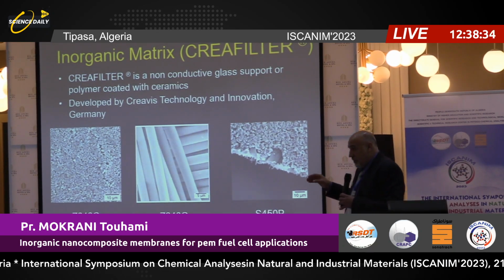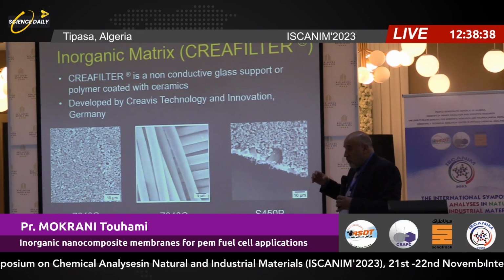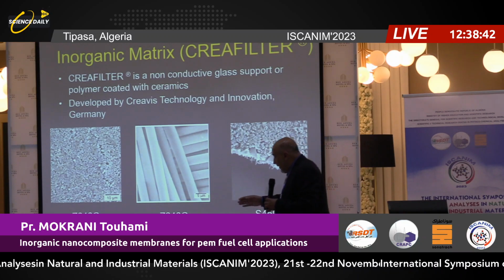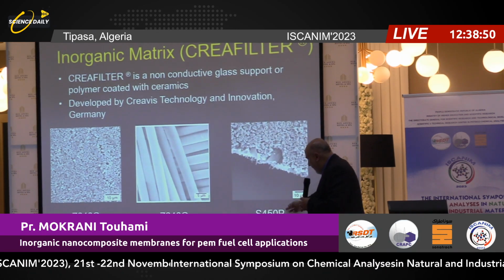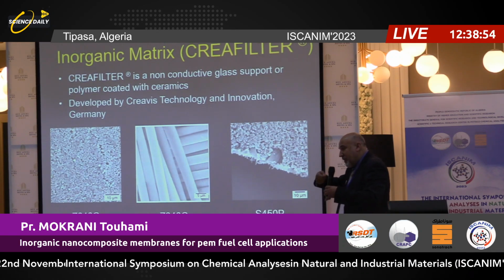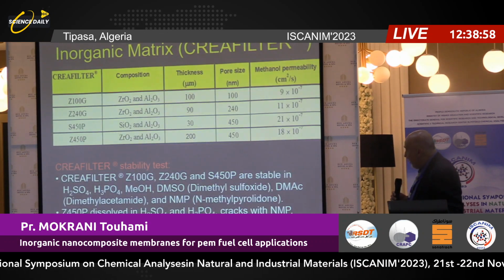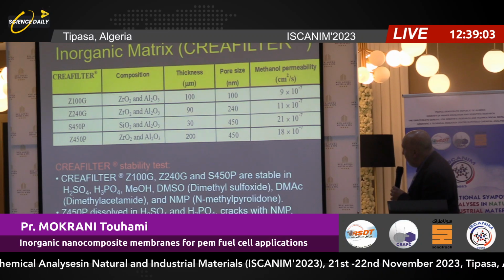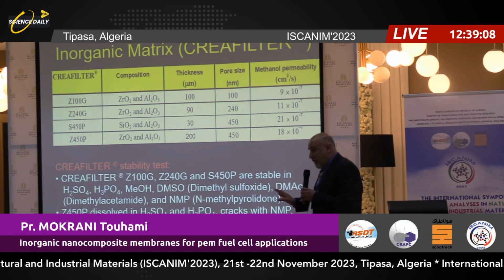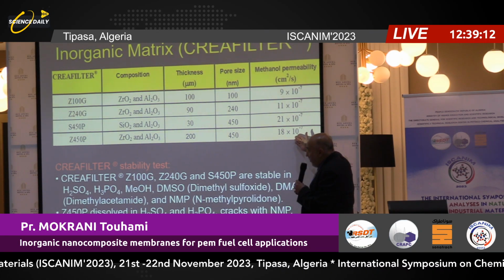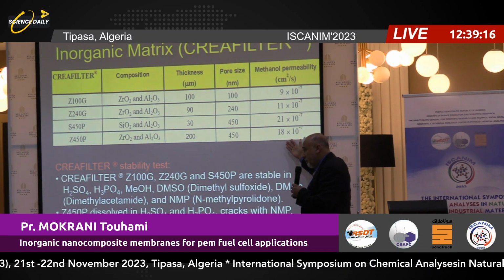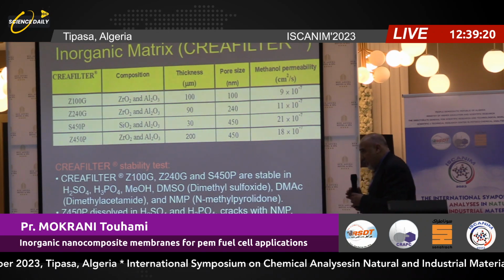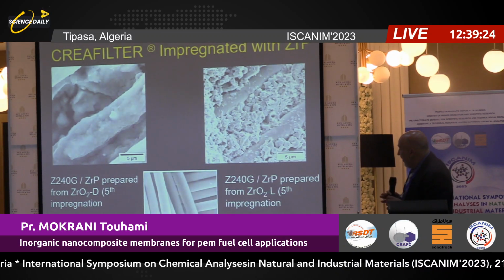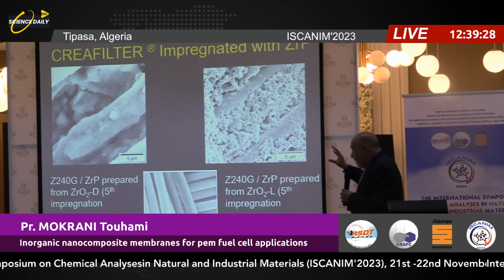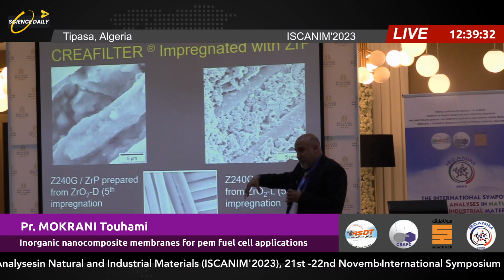So that's what we did in this. We prepared zirconium phosphate nanoparticles, but we also used flexible ceramic materials. This material is ceramic inner fibers. This one is from Degussa. Also, that's another material, also from them, the same principles. They call it a flexible ceramic. What we did, we checked the characteristics of the CREAFILTER as it is, without any filler. So we can see the permeability, which is very important at the end of the membrane. And that's the solubility of the material, or the stability of the material. That's the matrix. What we did, we impregnated it with zirconium phosphate. First, we took the base material, and we impregnated zirconium phosphate.